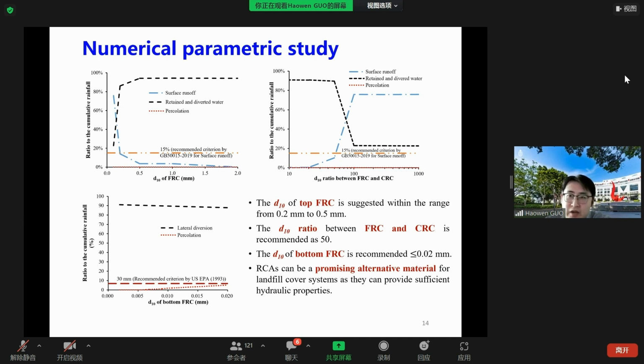As shown from the top right-hand figure, the surface runoff increased with the improvement of the D10 ratio between the FRC and CRC layer from 10 to 100. The reduction in the returned and diverted water is very solid when the D10 ratio increases from 10 to 15. It can be found that the surface runoff, returned and diverted water is almost not changed when the D10 ratio increased more than 100. So as a result, the D10 ratio between FRC and CRC layer is recommended as 50. This combination can provide sufficient return of the soil water as well as meet the design criteria.